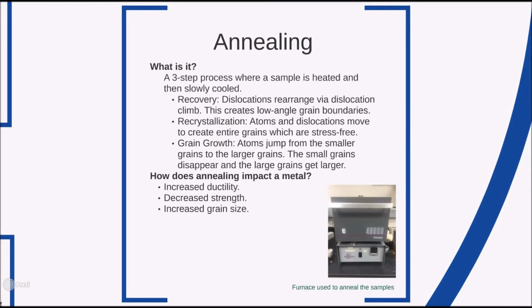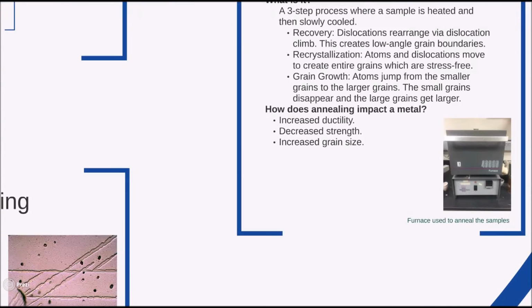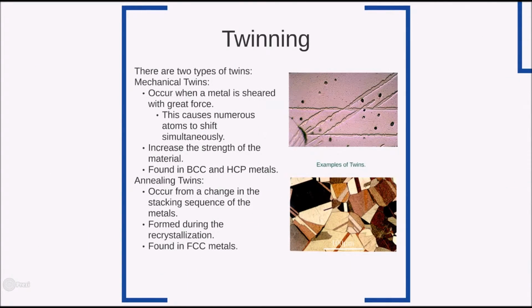When observing a metallograph, something called twinning may be observed. There are 2 types of twins: mechanical and annealing. Mechanical twins occur when the sample is sheared significantly. This force dislocates numerous atoms simultaneously, which all shift within the material. Since this is a dislocation and creates an area of non-uniform structure, it increases the strength of the material. This type of dislocation can be found in BCC and HCP metals.